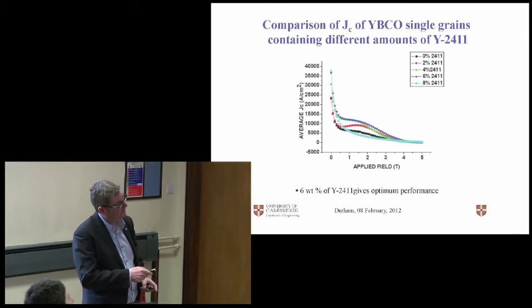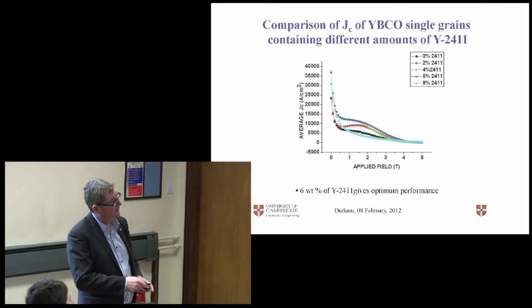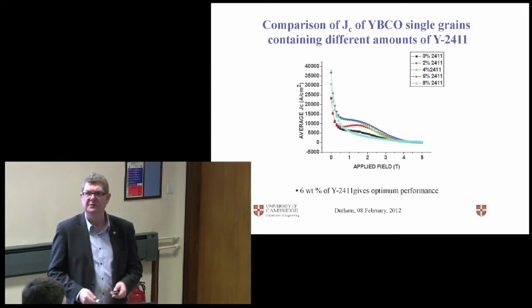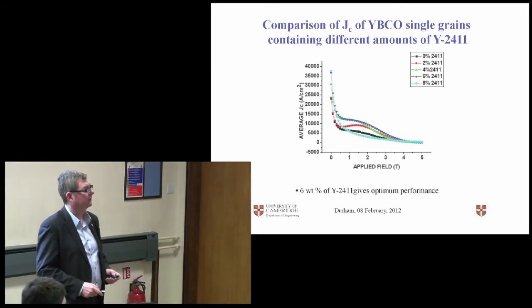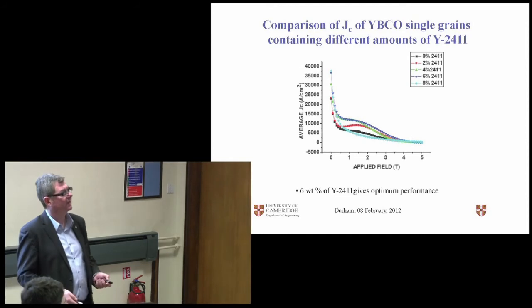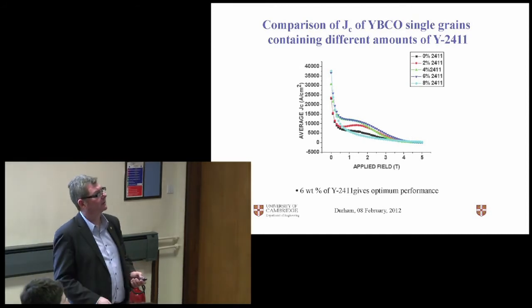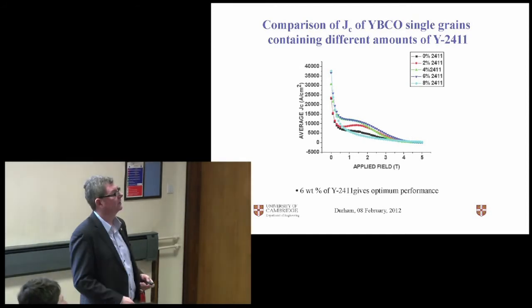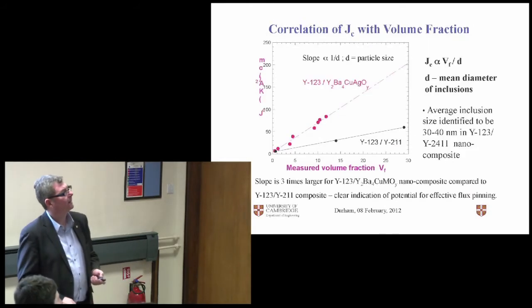But around about 6 to 8% 2411, we get this big increase in JC. So more than a factor of 3 increase at intermediate fields where these materials are more likely to be applied. So about 6 to 8% is the level of enrichment that we're looking for. So we have this at the powder processing stage.